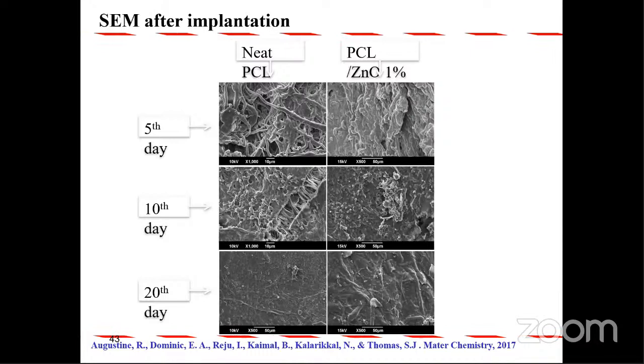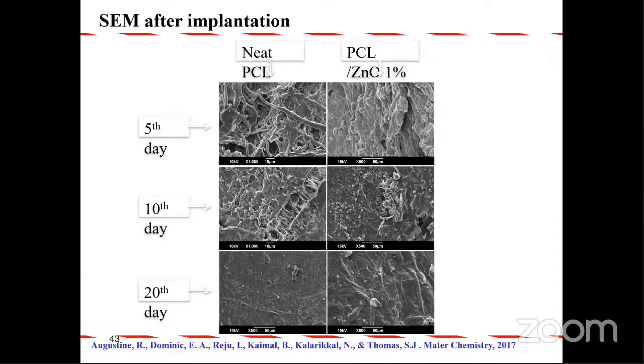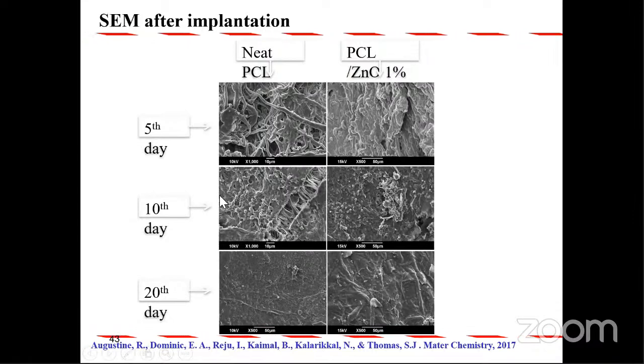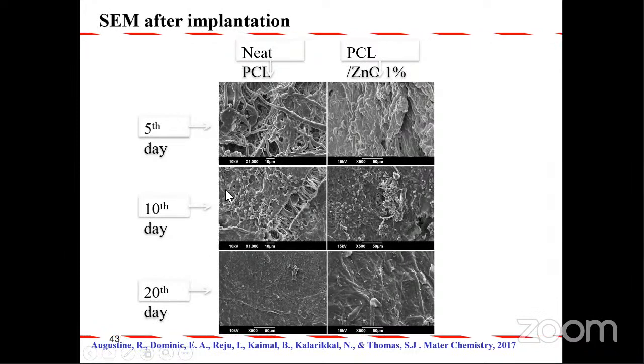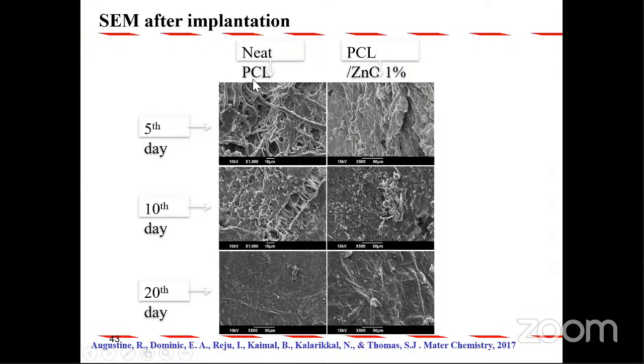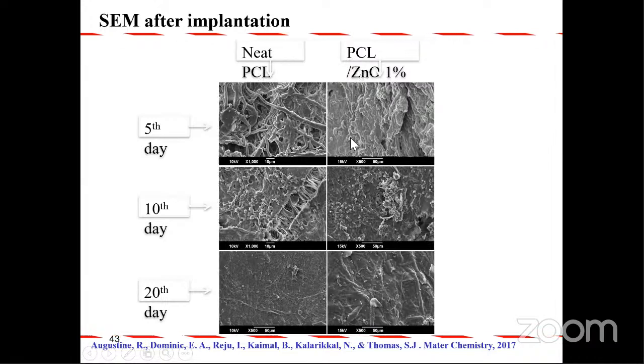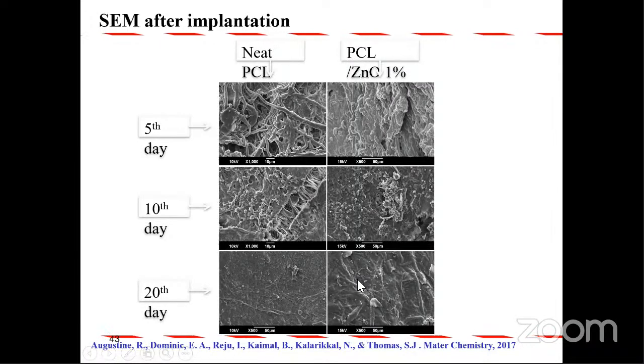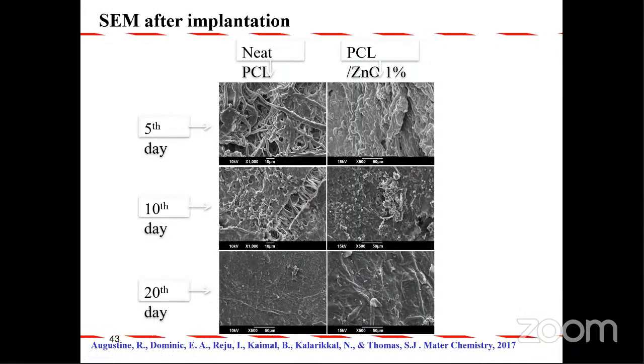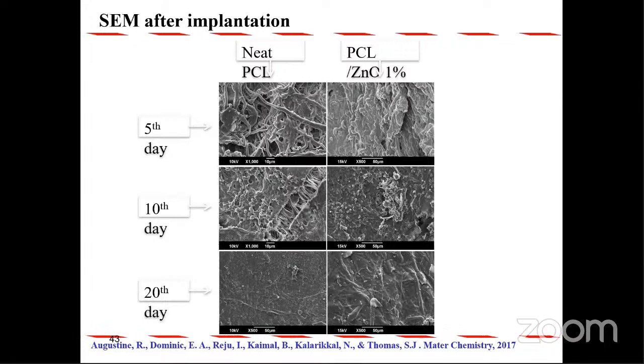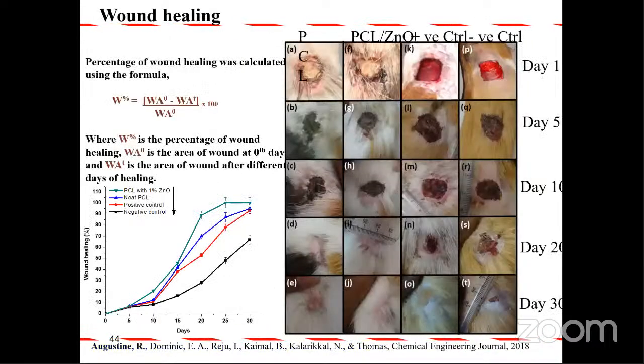We also looked at the degradation process. You see, after a while, your scaffold should disappear. This is 5th day, 10th day, 20th day. Look at this. This is neat PCL. This is neat PCL with 1% of zinc oxide. If you put a little bit of zinc oxide, there is a dual advantage. The wound healing is fast, and also after a couple of weeks the degradation is fast, because eventually the scaffolds have to degrade.